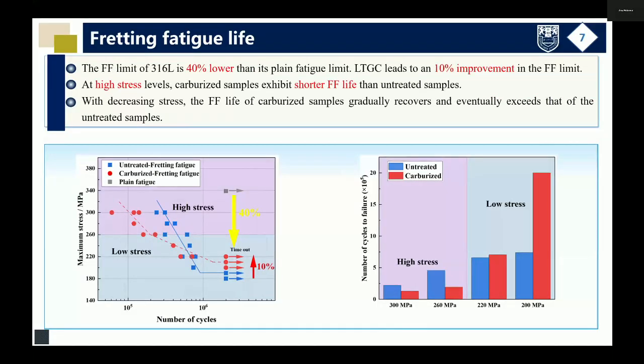Next, I will describe the results of the fretting fatigue tests, starting with the fretting fatigue life. The fretting fatigue limit of 316L stainless steel is 40% lower than its plain fatigue limit. LTGC leads to a 10% improvement in the fretting fatigue limit. At high stress levels, it should be noted that carburized samples exhibit shorter fretting fatigue life than untreated samples. The number of cycles to failure graph on the right shows that with decreasing stress, the fretting fatigue life of carburized samples gradually recovers and eventually exceeds that of the untreated samples.